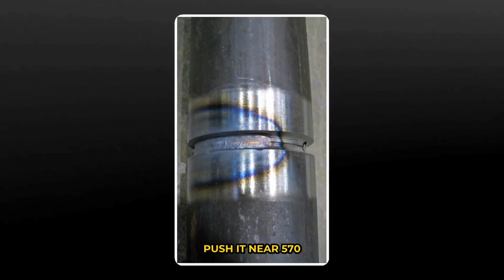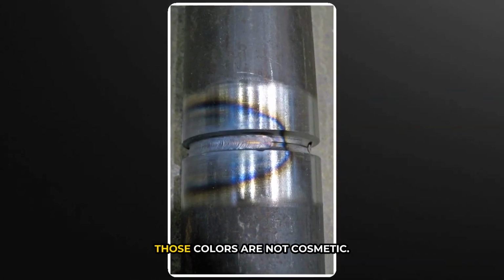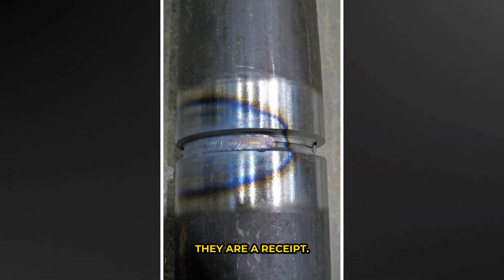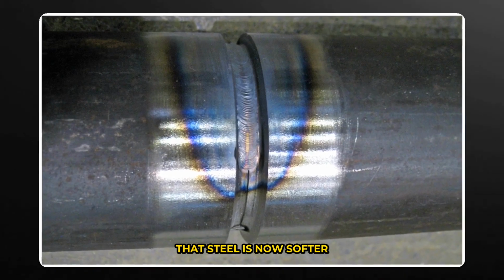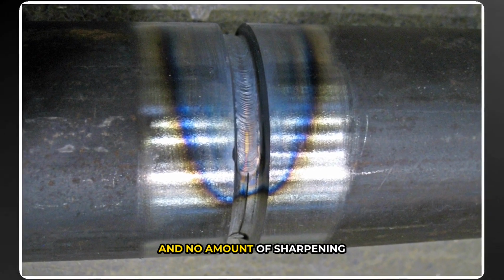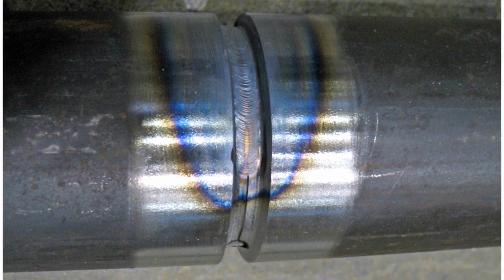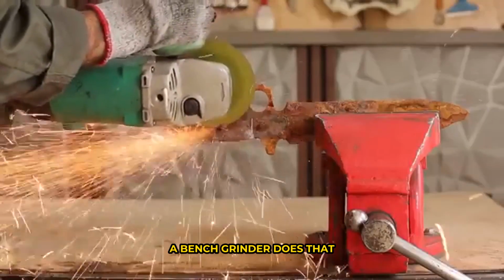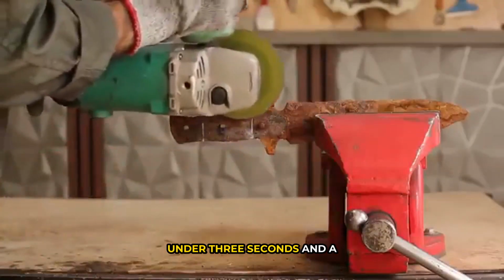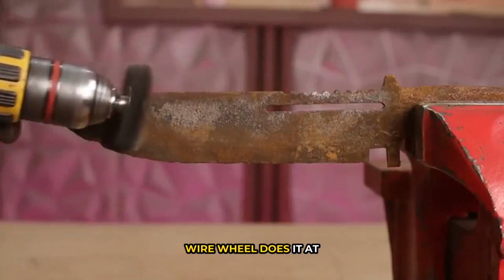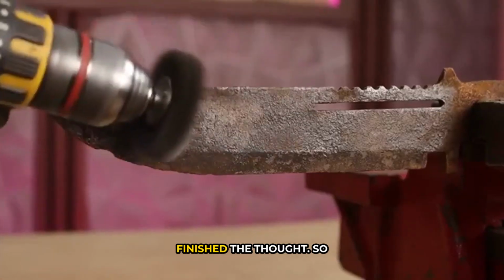Push it near 570 and you get blue. Those colors are not cosmetic, they are a receipt. That steel is now softer than it left the factory, and no amount of sharpening brings it back. A bench grinder does that to a thin edge in under 3 seconds, and a wire wheel does it at the tip before you have finished the thought.